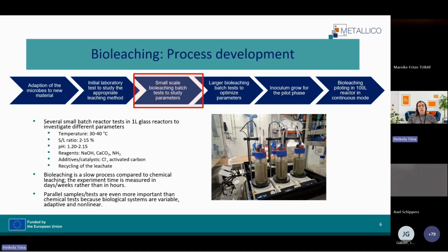Then we continued the work with the several small batch reactor tests in 1 liter glass reactors to study the effect of different parameters, including temperature, solid liquid ratio, pH range, as well as the chemicals for the pH adjustment, possible additives and catalysts to enhance the leaching efficiency and rate, and also recycling of the bioleaching leachate. In general, as already mentioned, bioleaching is a slow process compared to, for example, chemical leaching, and the experiment time is measured in days or even weeks rather than in hours.